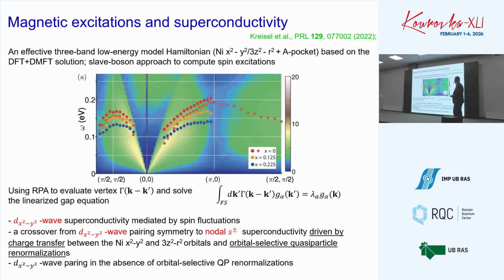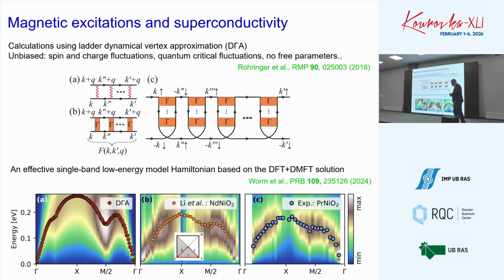This is a combination of dynamical mean field theory and random phase approximation to relate both the superconducting tendencies and this paramagnon-like spectrum, and the results are quite impressive in comparison. I would say not that bad. What is important is that they do see x squared minus y squared wave superconductivity, somehow similar to cuprates, although it competes with a nodal s plus minus state. With fine tuning, it's possible to switch between x squared minus y squared and s plus minus.